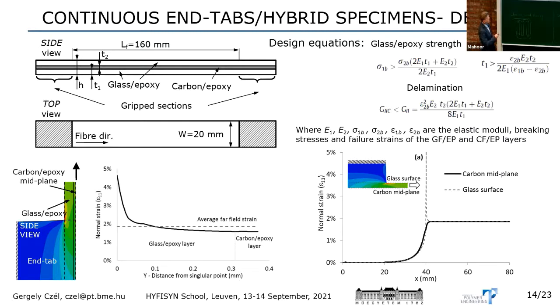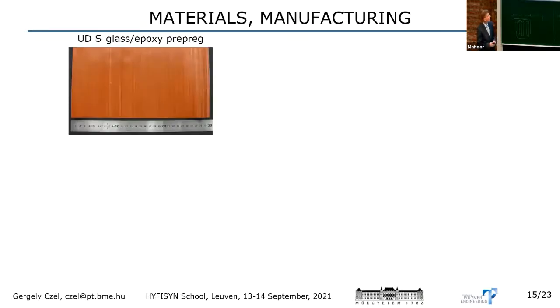Also, if we plot in the longitudinal direction the strains at the glass surface and the carbon midplane, we can see that this high peak is absent completely in the carbon, which is of interest for us for developing the test method. So we can conclude that it is possible to fully eliminate the stress concentrations if we are using these full protective layers on our specimen.